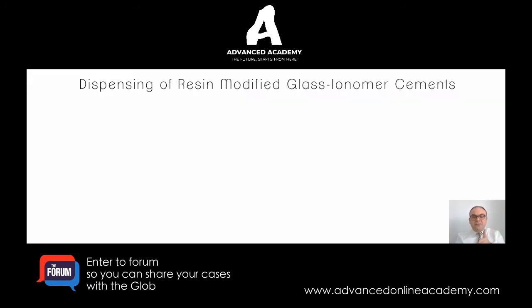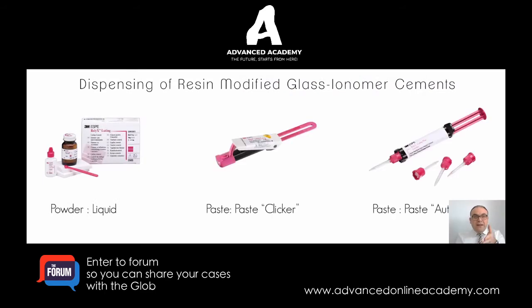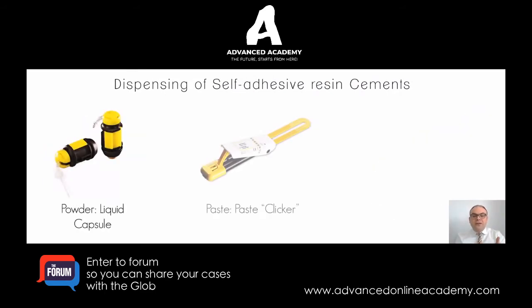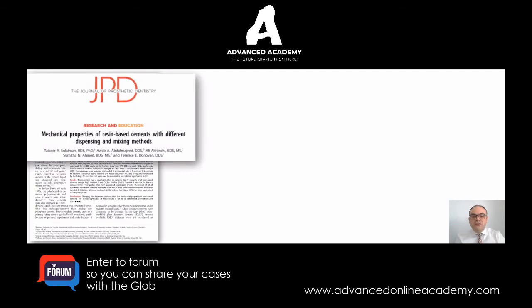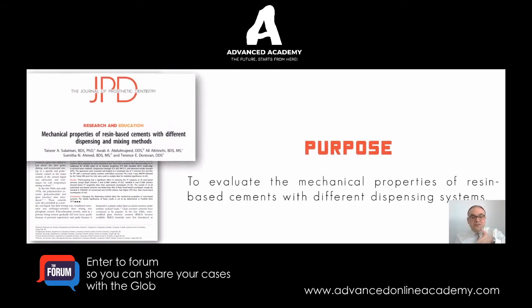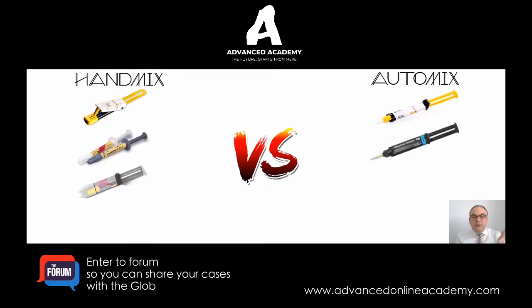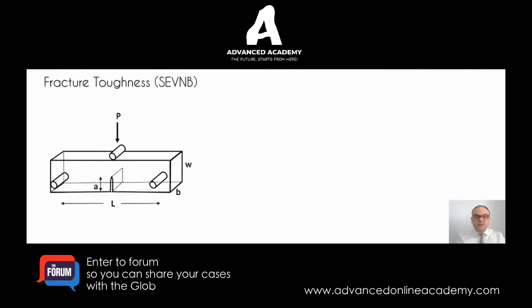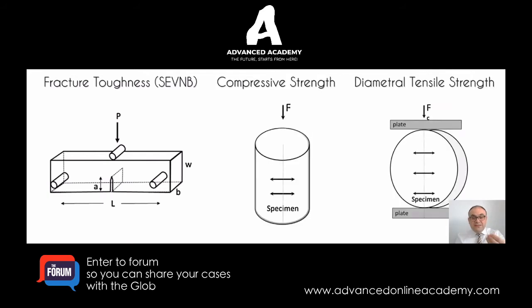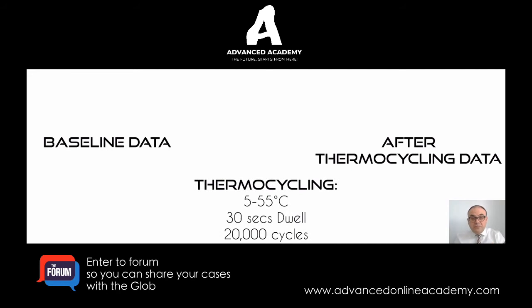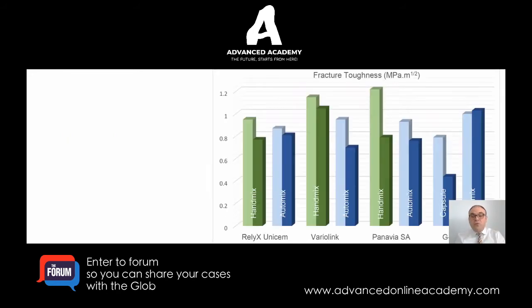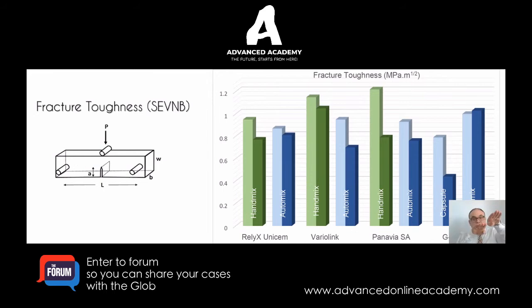Just to wrap things up, I know I went over my time a little bit, but I really wanted to share with you the different dispensing methods of different cements. Within a brand, there are different dispensing methods. This is another example of a resin cement. You have powder, liquid, clicker, and you have the auto mix version, which is 4 papers looking into these different types of cements. We compared multiple cements in their hand mix version to the auto mix version. We did strength testing to see the mechanical properties. We aged them so that we can see how these cements perform with time. You can see the aging process reduced the properties of the cement, just like we were expecting.